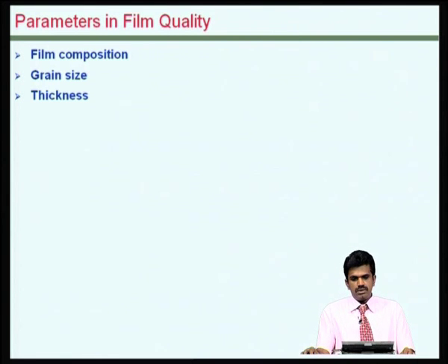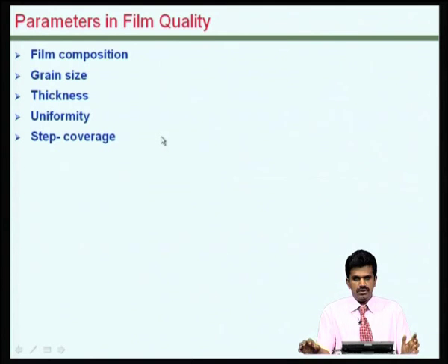Thickness can be controlled, but yet the thickness that can be formed, as well as the uniformity of the thickness of the film that can be realized, is obviously important in realizing good quality devices. In the context of deposition of films, another important parameter is the step coverage. This happens when you are depositing a film onto a geometry that is already formed, and see, for example, you have a wafer in which some kind of structure is formed, which has a step variation